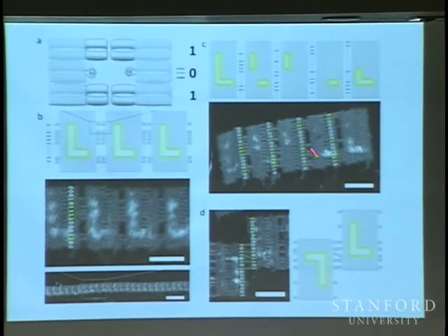In general, constructing such codes is formally NP complete, but you can get a small set of good codes fairly easily, and that's what he did, especially since we're only putting 5 together. But if we wanted to put hundreds together, it would be much harder to get good codes. But he's come up with good codes. Here you can make them form long chains where they're all oriented correctly, and they do have errors. The kind of errors that they have, unfortunately, are mostly these off-model interactions.